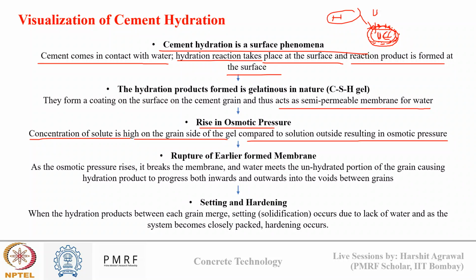Now once this pressure rises above a critical limit, what happens? It will break the membrane. Once the membrane is broken, what happens? Water meets the unhydrated portion inside, while the unhydrated cement tries to move outside, and there is hydration of the cement grain, and the voids between the cement grains also start to fill up as hydration happens outside also. Okay, so when two cement grains start to merge together due to hydration, we say that setting has started.